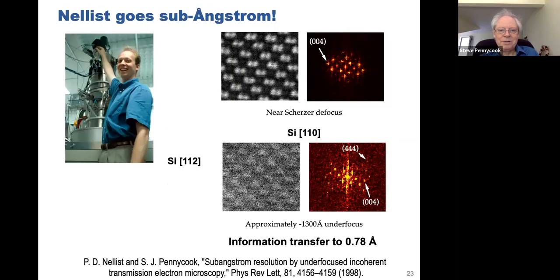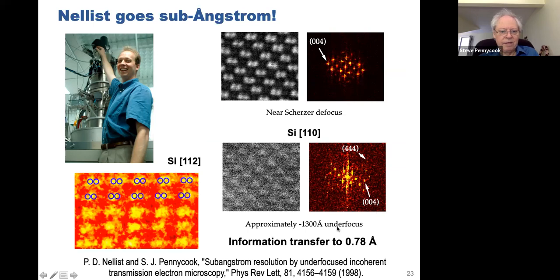Pete Nellist was there at the time, and of course, Pete, never satisfied with splitting the dumbbell, had to go and try and go sub-angstrom. And indeed, he did go sub-angstrom. You can see the transfer here. He did it by going to a large underfocus and got information transfer to 0.78 angstrom. The image was pretty noisy, but clearly elongated pairs of atoms. So kind of resolution of a sort.